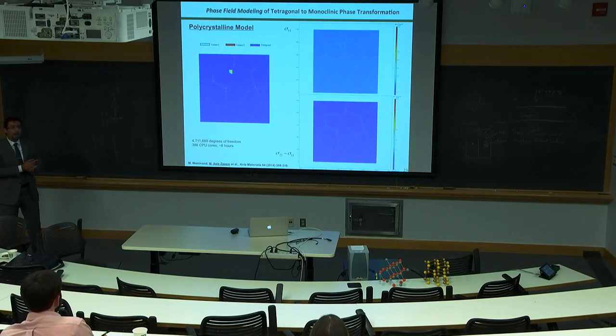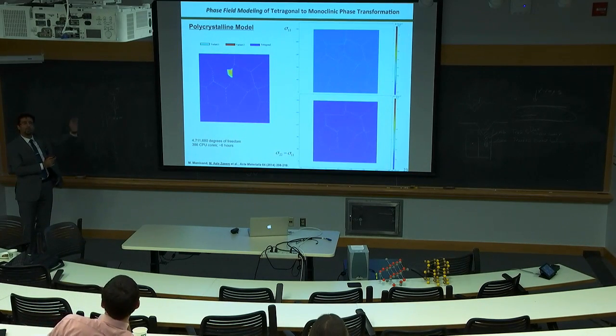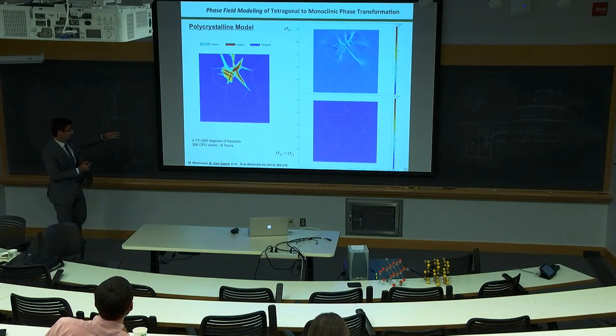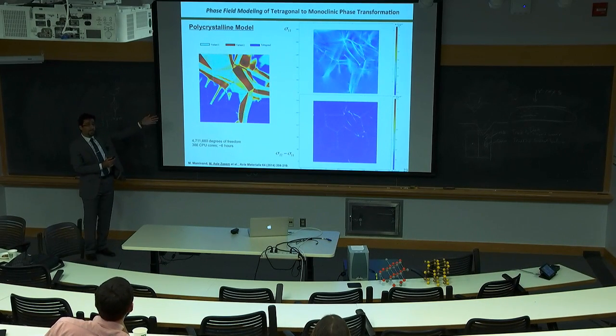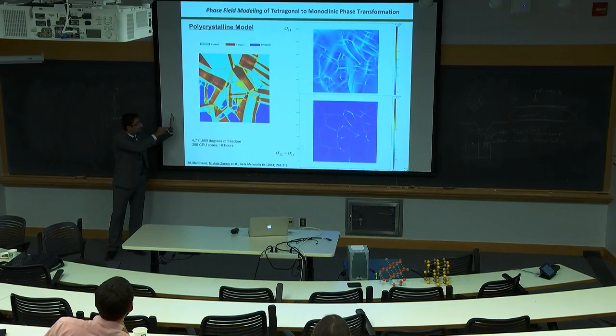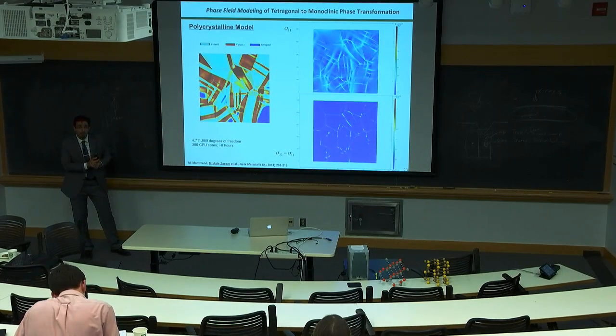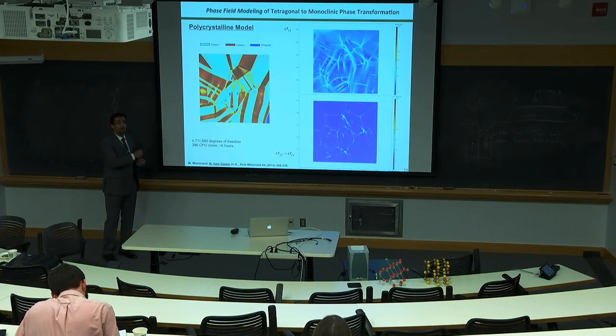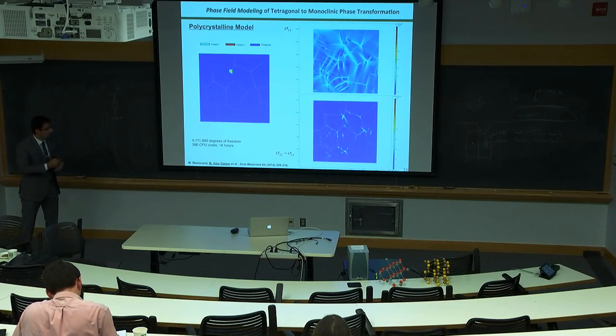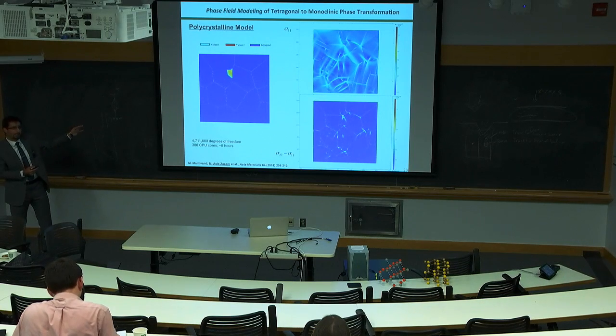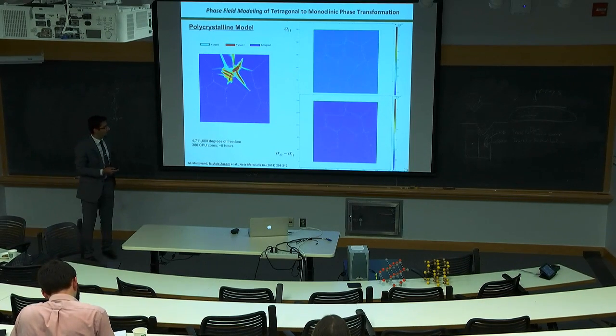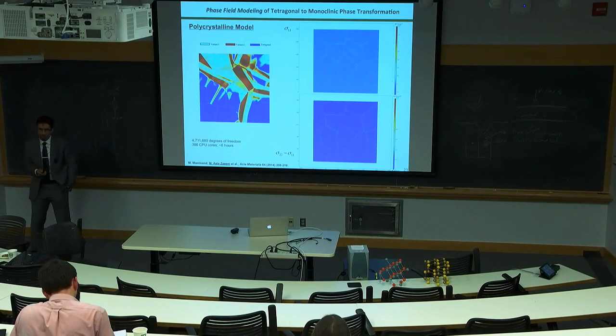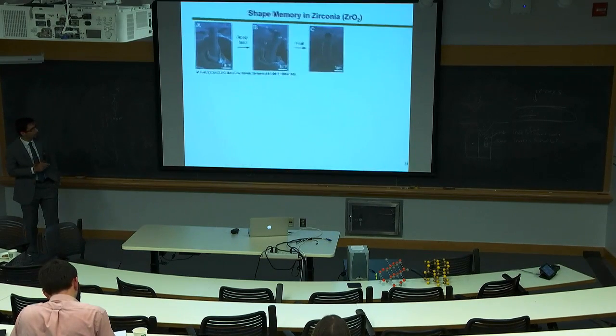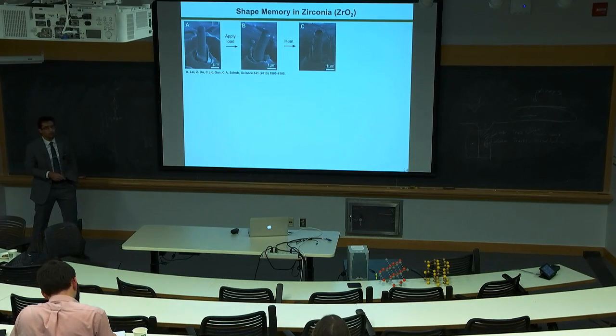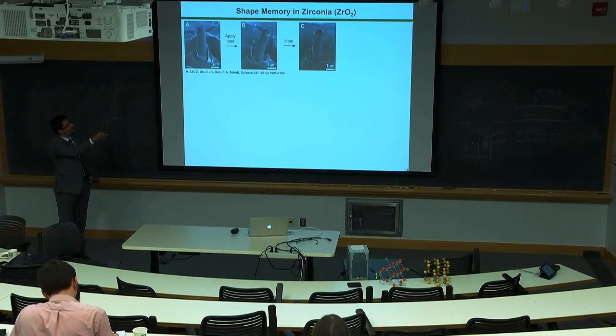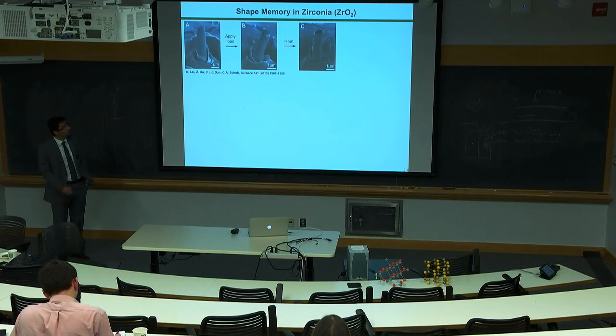In reality, we have polycrystalline systems. Those that I showed you were just single crystal. So for polycrystalline, I didn't put the equations. They're going to get really messy here. So for grain boundaries, you need to have all the grain boundary energy information transferred to this model, and we did it already, and these are the patterns. While we were doing these simulations, we found that zirconia has many other applications. In 2013, I found a paper published in Science that shows that zirconia has this property which is called shape memory.